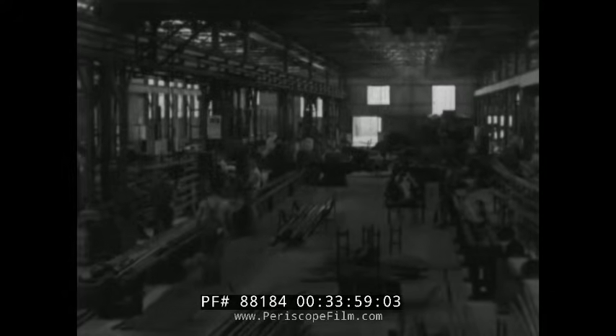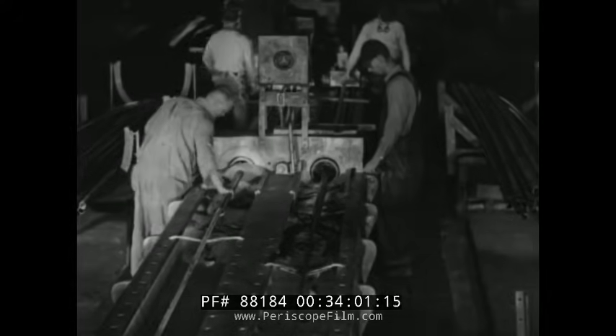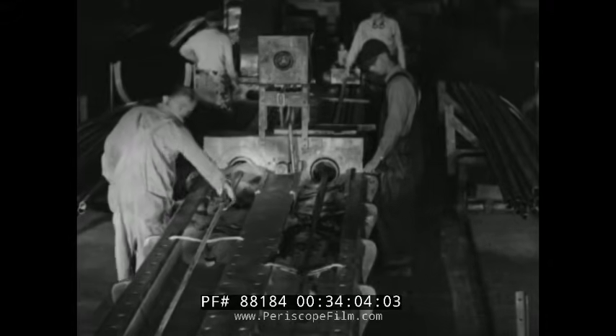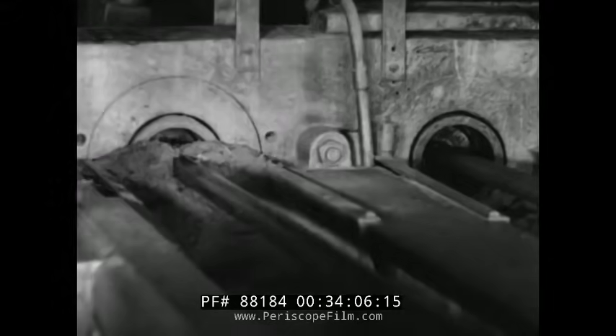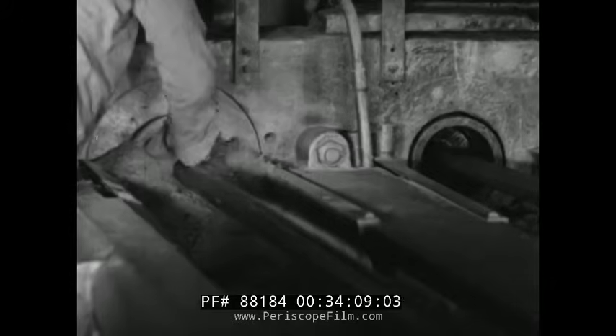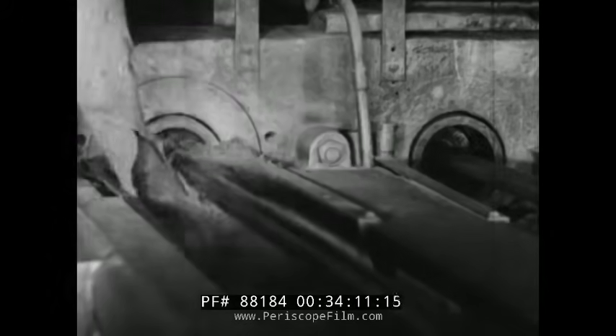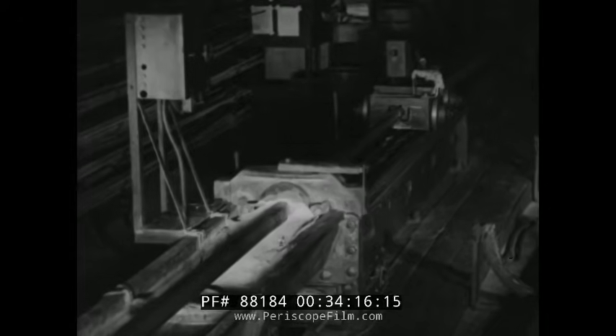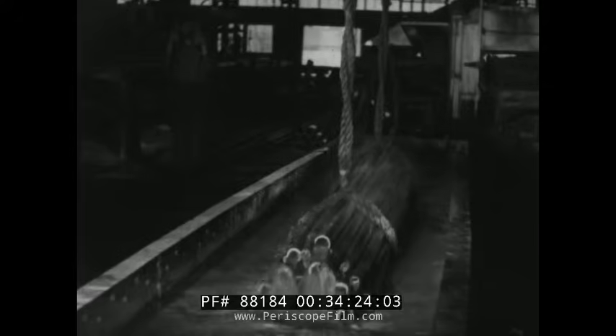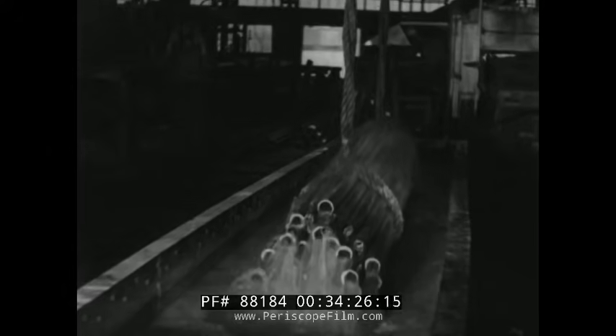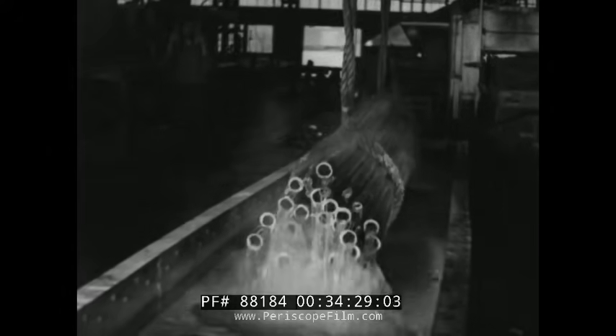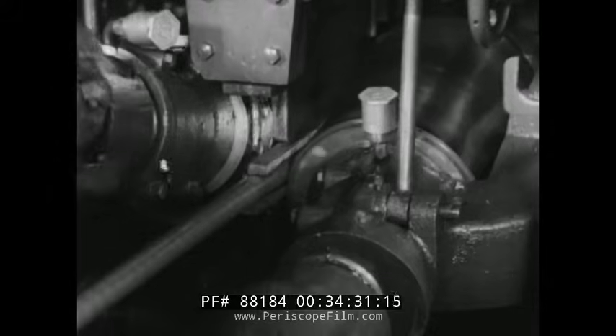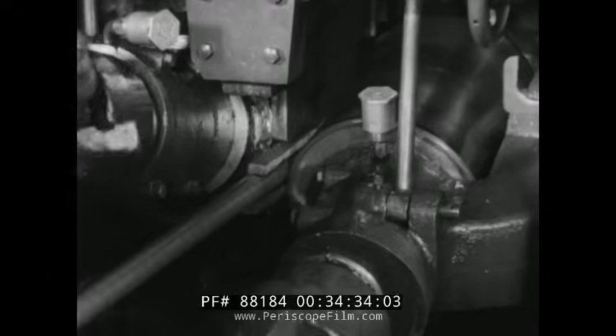Cold-drawn products are processed in this department. The draw benches in this department are of various sizes. Some draw 2 bars or tubes at a time. This draw bench is both roughing and finishing. This heavy bench will draw seamless tubes of about 4 inches in diameter. Reduces both the wall thickness and the diameter at the same time. Before tubes are annealed, it is necessary to wash off all traces of lubricant. The rods are very accurately straightened in a Medart machine.